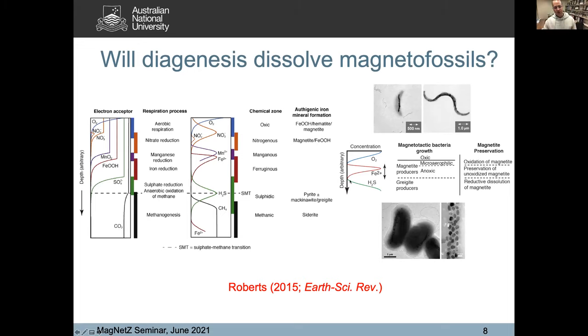When you get into this sulfidic realm, magnetite dissolves — it's unstable and won't be preserved. Magnetite is preserved in the oxic to nitrogenous to ferruginous zone. Greigite producers will occur deeper where it's sulfidic, and there's not a huge amount of work yet on greigite producers, which I think is a real pity. I expect them to be really common in the geological record. The particles look ratty, they form poor chains, they're poorly crystalline — it's a tricky problem but one that deserves attention.